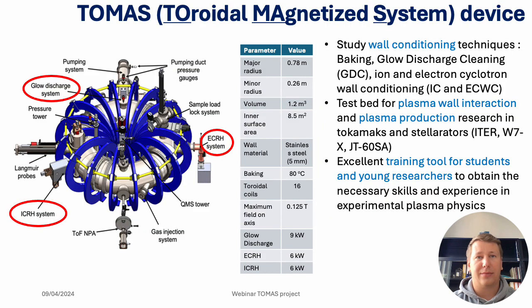optimization. The TOMAS device is a toroidal stainless steel device with a major radius of 78 centimeters, which is the distance from the device center to the center of the plasma chamber. It has a minor radius of 26 centimeters, which is the vacuum chamber radius. The vacuum vessel can be baked out with an average temperature of 80 degrees Celsius, allowing for baking studies. The device has 16 toroidal magnetic field coils, providing a magnetic field of up to 125 millitesla on the device axis. It's in the middle of the vacuum chamber.